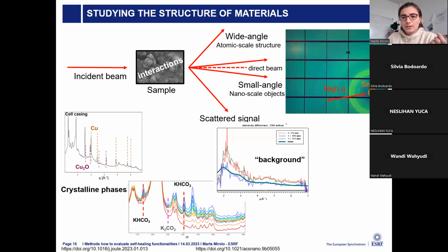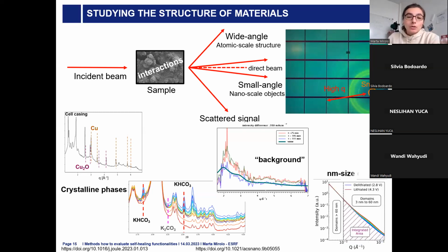So the background contains information. For example, we can look at where the electrolyte is accumulating, as an example. And then we can also look at the small angle X-ray scattering, which gives us information at the nanoscale object, for example, at the swelling of nanoparticles.